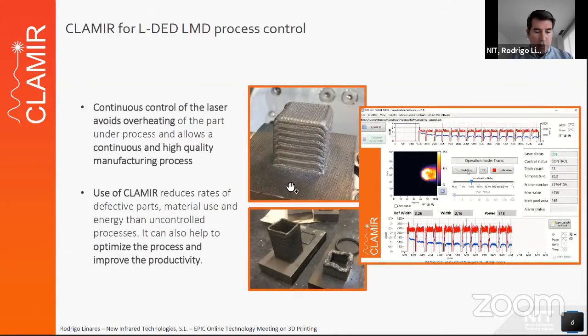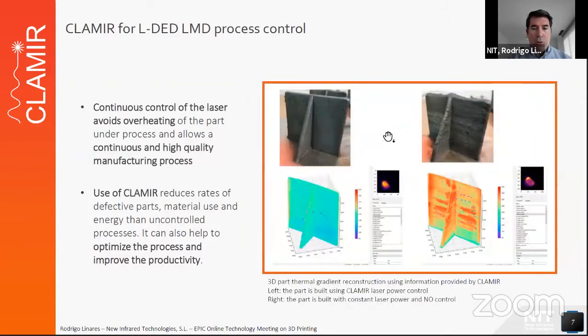With Clamir, it's possible to have a continuous and high quality manufacturing process, such as in the cuboid that I'm showing here. Here you can see how Clamir was controlling the laser power, that's the blue line that you can see here, while maintaining the melt pool width constant. And the consequence of this is a continuous processing and a high quality manufacturing process. Also, Clamir can help you to optimize the process and improve the productivity.